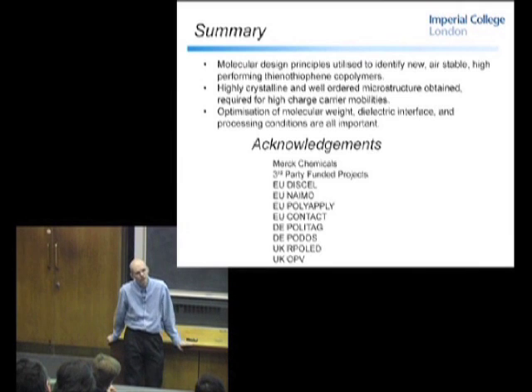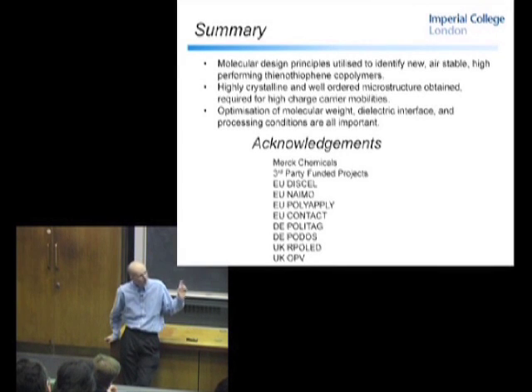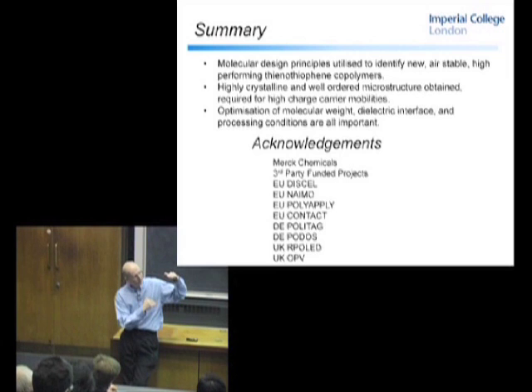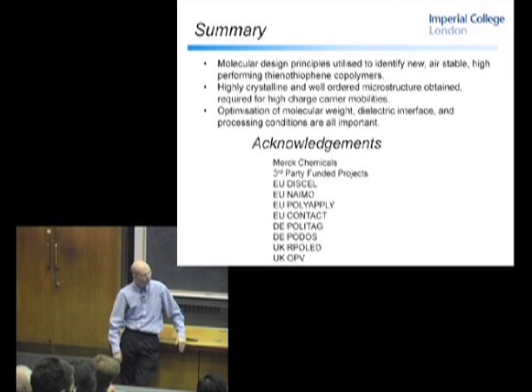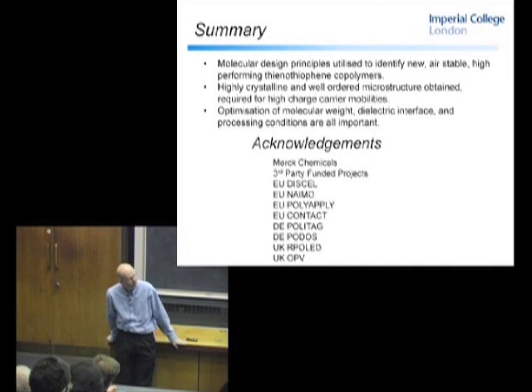I think that the electron transport was maybe 1 or 2 orders of magnitude lower than the hole transport. That's not the case in time of flight measurements. In time of flight, hole and electron transport for even thiophene materials is quite similar. I mean, there are other reasons why a field effect device, so the way you inject the charge in a transistor, you have to inject it from the electrodes. So if you have a barrier, or maybe a high work function electrode, it's hard to inject electrons. Whereas with time of flight, you're photo generating the charge, so there's no issue of injection barriers. So you can see the electron transport much better by time of flight.